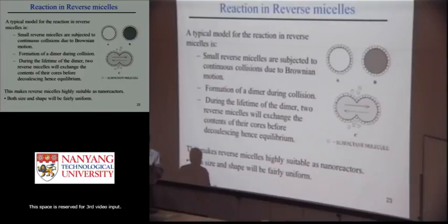So in the preparation process, typically we have to dissolve A, the precursor, into the water before forming the microemulsion. So this will be a problem. You see, if I add A and B together in the water, they are mixing. Maybe the reaction started before I form the microemulsion, and you lose the control of the size. You lose the control of the shape. So how can we control A and B so that the reaction only happens when the microemulsion forms? We can make two microemulsions.